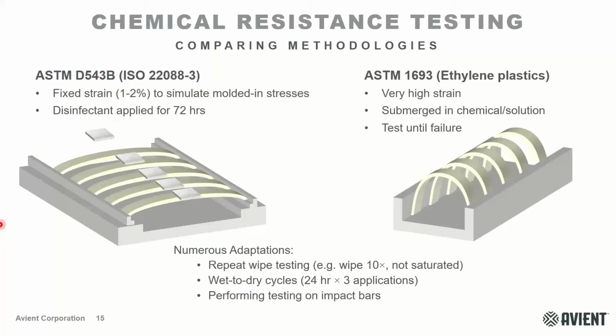And then what you do is you'll apply a disinfectant and a gauze soap pad to the middle of these bars for 72 hours, typically 72 hours, but there's a lot of different adaptations, some of which are listed here below. For example, instead of applying a gauze soap pad, you could do repeat wipe testing, which I've seen done in the industry.